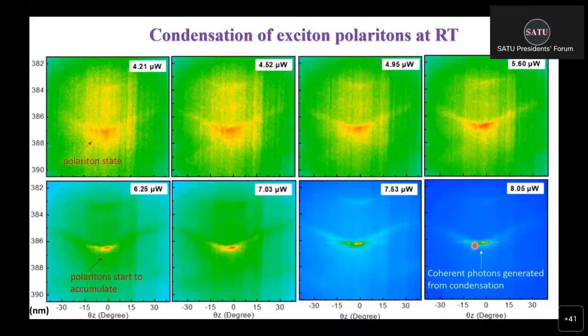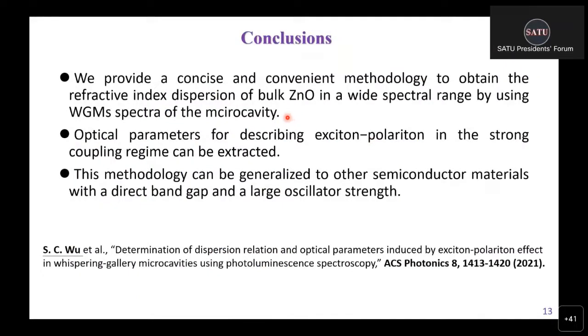So in conclusion, we provide a convenient methodology just based on the optical modes in the spectrum and the geometry of the microcavity. We can use this information to calculate the index dispersion, and we can extract the optical parameters. And most importantly, this methodology can be generalized to other semiconductor systems with a direct bandgap and large oscillator strength.